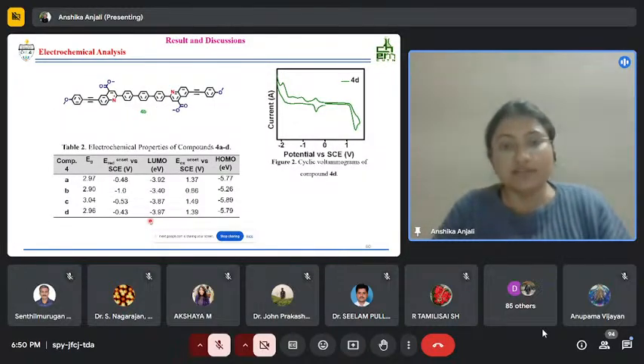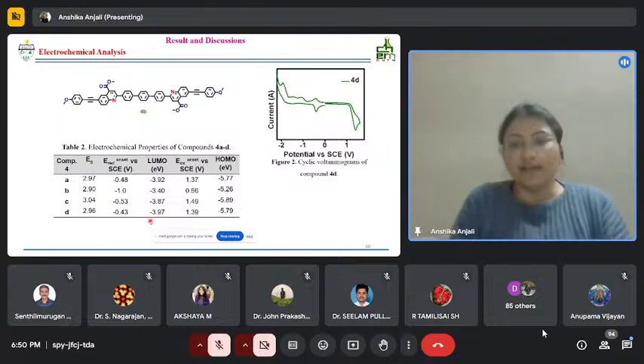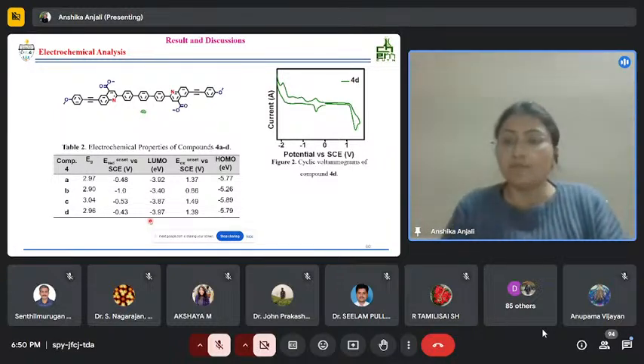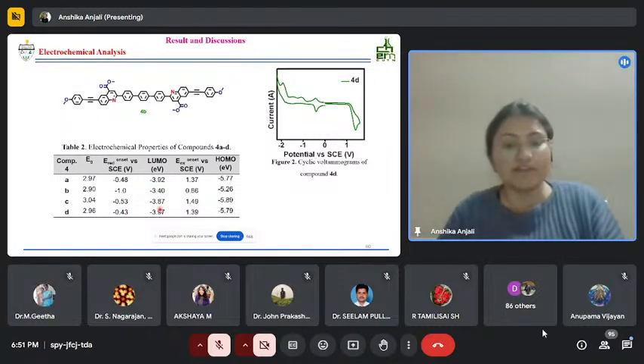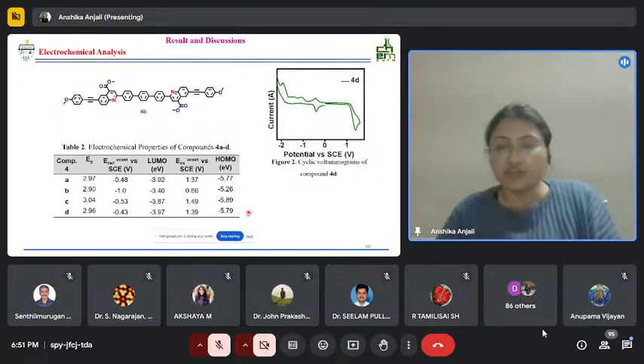Their cyclic voltammetric studies were also done, and in the cyclic voltammograms we observed peaks in both positive as well as negative potentials. From the onset reduction values we calculated the LUMO energy levels, and from the onset oxidation values we calculated the HOMO energy levels. Their LUMO energy levels are in the range of -3.40 to -3.97, and their HOMO energy levels were in the range of -5.26 to -5.89 electron volt. So these compounds have a band gap nearly equal to 3 electron volt.